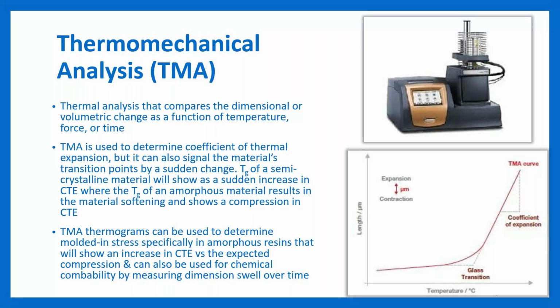The other thing that it can be used for, which is unique, not necessarily for failure analysis, but if you've seen data for chemical resistance that deal with volume swell, I see it more commonly with soft touch materials. So if you see like TPV materials that are exposed to different oils, ASTM oils and gases, it gives you a dimensional swell as a percentage versus time, and sometimes also with temperature as well. But this can be used to do something like that. So a unique way of getting a few different bits of information out of this test. And so great test for stuff like that.